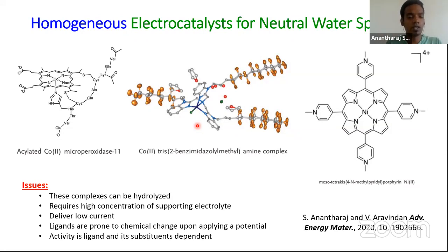So that is the reason this is facing huge difficulty. And because of very low concentration of catalyst dispersed, it also delivers low current intensity, and ligands are highly prone to chemical changes, because in water, when we apply electrochemical potential, we cannot rule out the possibility of further change in the chemistry of the ligands, which could also lead to the eventual hydrolysis of metal centers. So these are the issues with electrocatalysts.